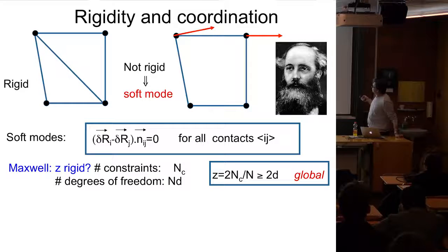So when do they appear? Well, you can think about what equations are satisfied by those modes. Those modes have to keep all the springs from changing length. That's this equation here. It's not really important to follow it, but n_ij is just the unit vector along the spring ij. This is just saying that the relative displacement in each spring has to be orthogonal to the direction of the spring, otherwise you would change the length. So it's a linear constraint, and you have a set of linear constraints, one for every spring you have.